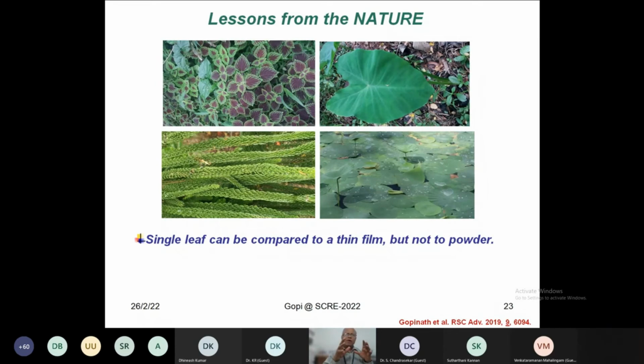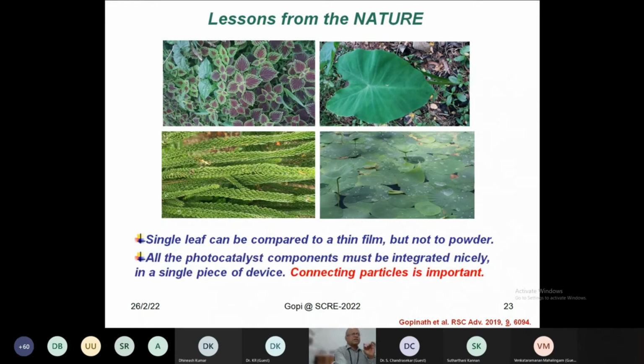So can we make our powder catalyst into a thin film? Just simply deposit it on a substrate and evaluate. That was the simple idea we generated. Then we did that, and the activity jumped at least 10 times. So then we realized that connecting particles is very, very important.